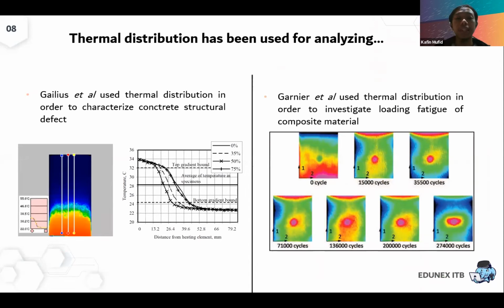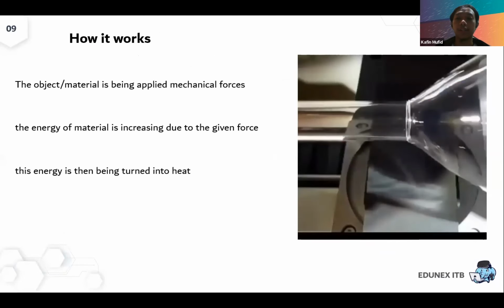Depending on the level of the concrete defect, the material will have a different thermal distribution, as you can see on the chart and here. And Garnier also used thermal distribution in order to investigate the loading fatigue of composite material. So depending on the fatigue level, the material might have a different thermal distribution. So this is at 0 cycles, and this is the very high cycle. So it's very, very different depending on the loading fatigue, right?